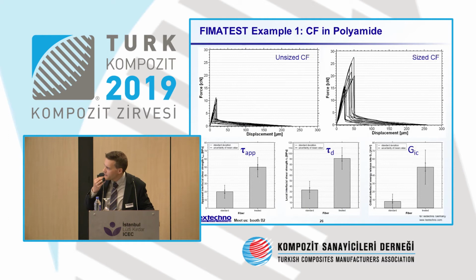Here, I think I've got 4 examples of different fibers and matrices that we've measured. This is a carbon fiber and polyamide. On the left-hand side, you see an unsized carbon fiber. On the right-hand side, you see how the pull-out curves look like for when the fiber received the proper sizing. You see that it already makes a huge difference in the test, even not looking at the derived quantities.